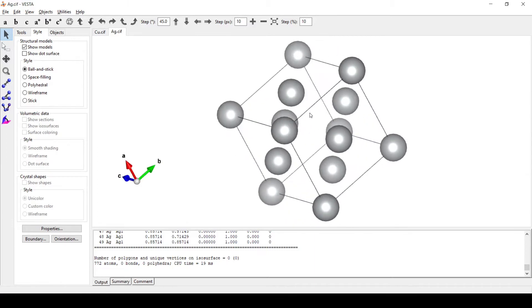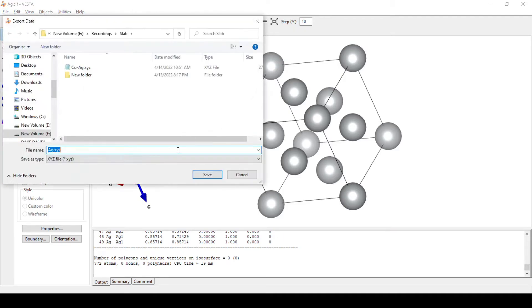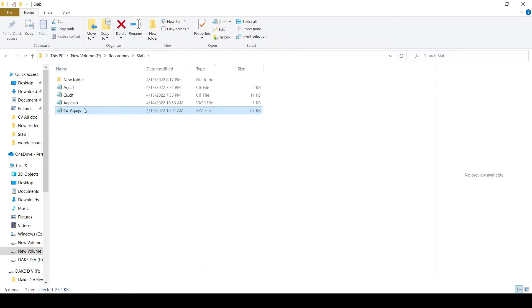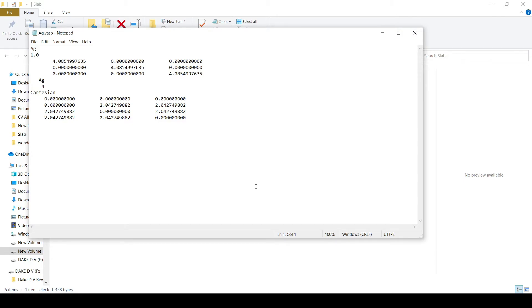Before that we will use this Ag file or Ag structure as a template. For this we will save it as a VASP file. Go to File, Export Data and save this as VASP with Cartesian coordinates. Here we can see our VASP file. We have to modify this file in order to generate the heterostructure. We will write copper — the number of copper atoms is 384, and the number of silver atoms is 294. We will add copper here and replace the Cartesian coordinates.